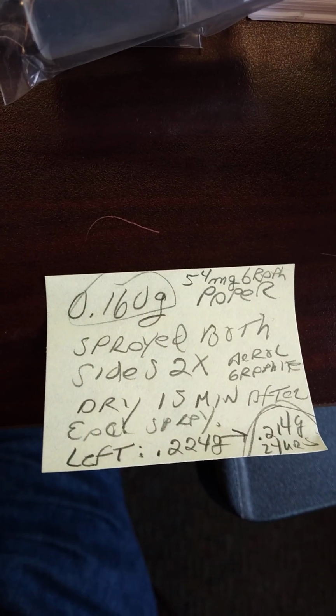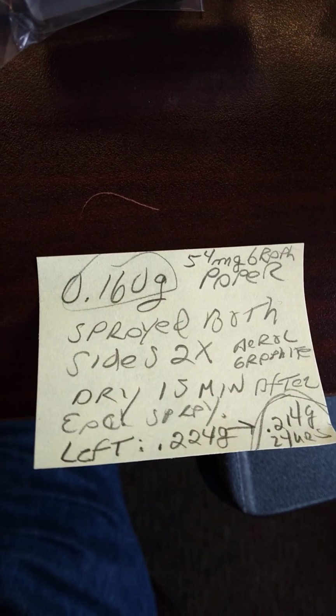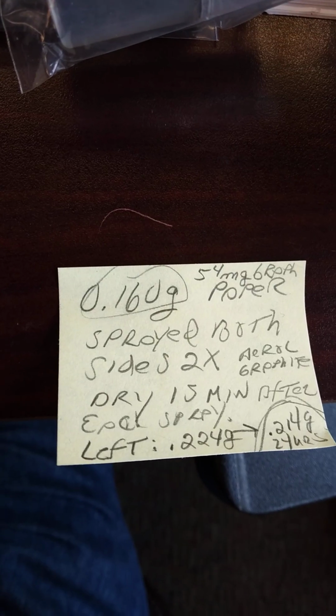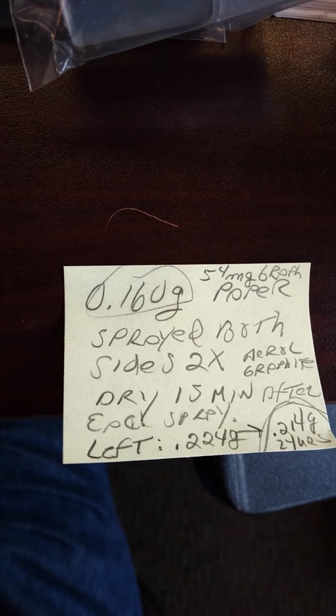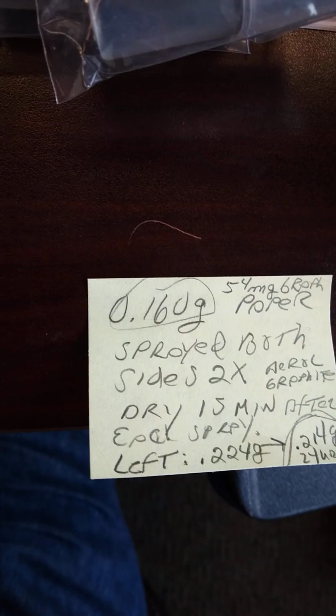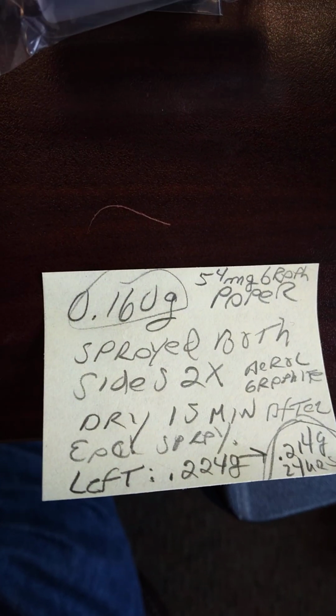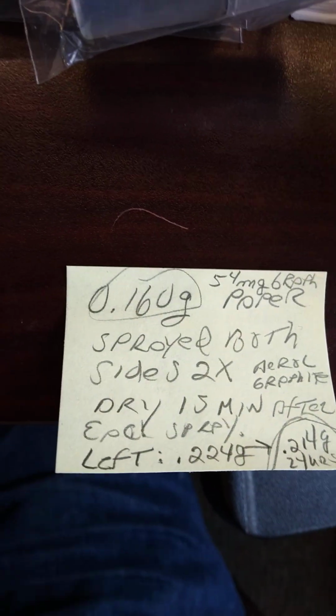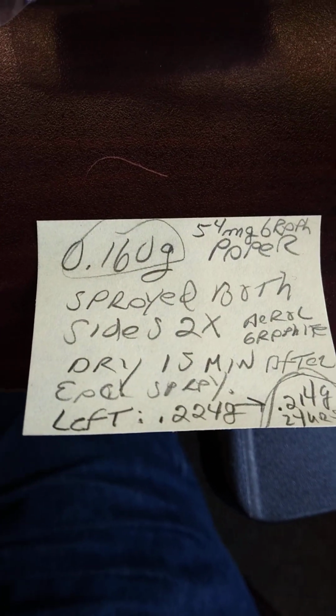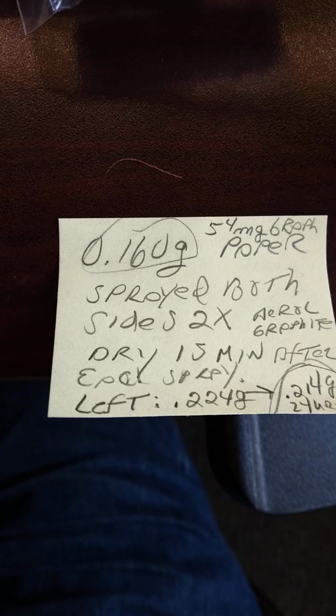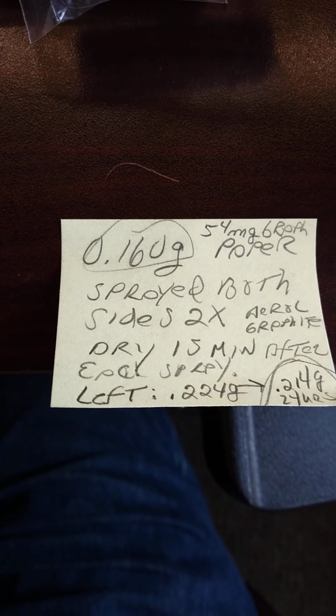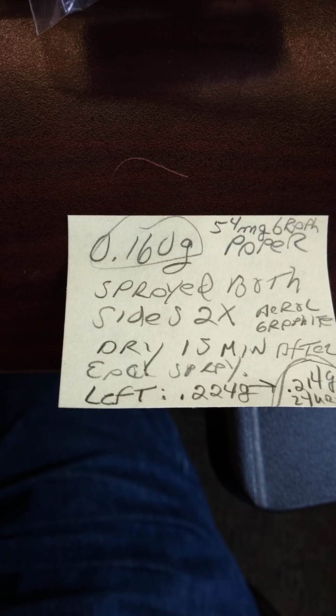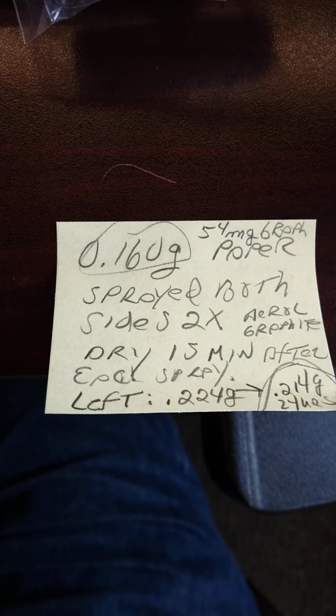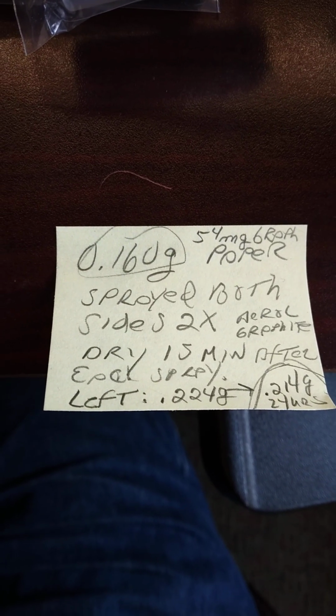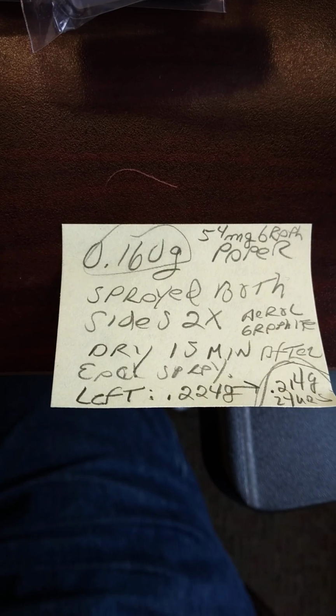It's important, of course, how you apply the spray. What we do is back and forth one side, let it dry 15 minutes. Now, the manufacturers say give it a minute, but I can smell the solvent. I don't know what solvent they're delivering this with, but I give it 15 minutes to dry. Then apply a second coat uniformly at a distance of 12 inches. We try to be consistent. Another 15 minutes. Flip it around, repeat the process.